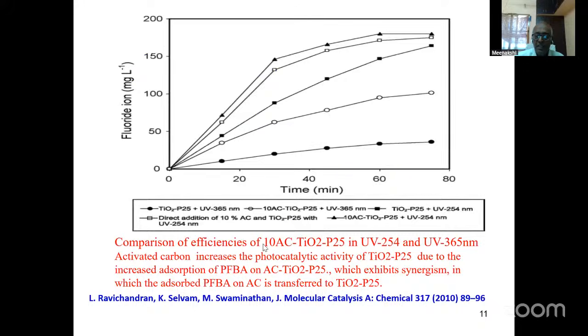And this is the degradation of pentafluorobenzoic acid and pentafluorophenol. And this is for pentafluorobenzoic acid. You know that one of my students was working in the TANPAC industry, where he had pentafluorobenzoic acid and pentafluorophenol in the effluent. Then we wanted to degrade that pentafluorobenzoic acid. We started using 10% activated carbon loaded TiO2 P25 with two different light wavelengths. And we found that 10% AC TiO2 P25 was most efficient in degrading pentafluorobenzoic acid.